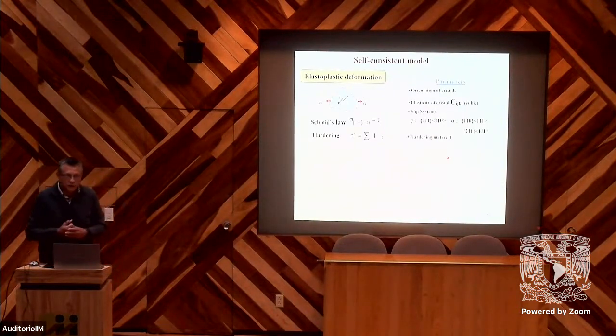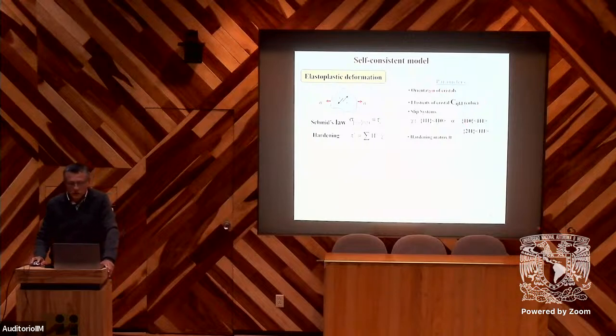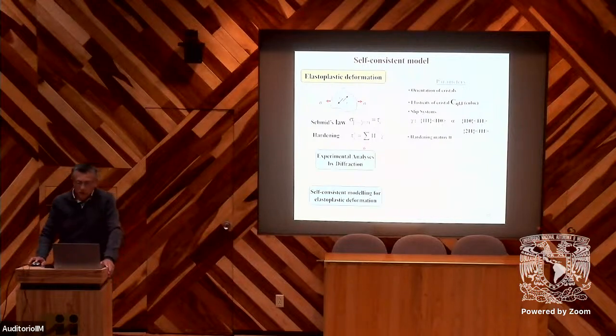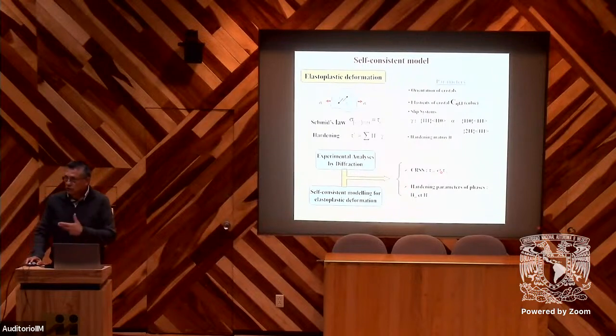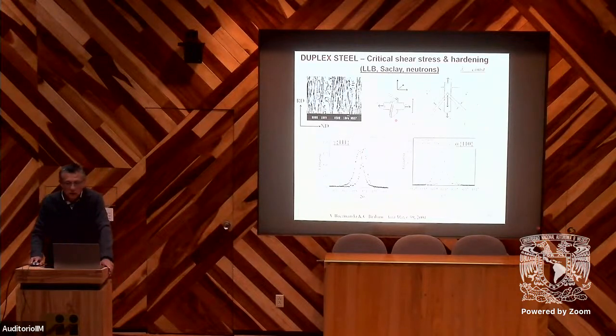To study the behavior of each phase, we need a model. For this, we use the self-consistent model. For this model, we need some information concerning, first, the orientation of crystals, the elasticity of crystals, the slip systems for the two phases, and also the hardening matrix. Now, if we measure what happens during the loading by diffraction, and we compare it with the self-consistent model, then we can obtain the different parameters to describe the behavior of each phase. That means we need the critical shear stress and also the hardening parameters for the two phases.